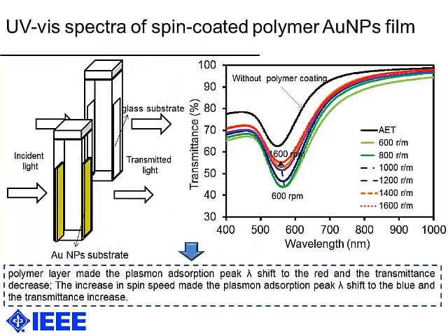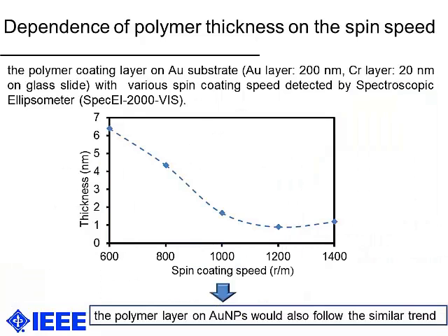And then we detected the spectrum of spin coating the polymer on AuNPs films with different spin coating speeds, shown like this one. The polymer layer made the plasmon absorption peak lambda shift to the red and the transmittance decrease. The increase of spin coating speed made the plasmon absorption peak lambda shift to the blue and the transmittance increase. And we used an ellipsometer to verify the dependence of polymer thickness on the spin coating speed. Here, the Au substrate is shown like this. The Au layer is 200 nanometers, and then we dripped the same amount of polymer liquid with different spin coating speeds. The thickness value is shown like this one. So the polymer layer on Au nanoparticles should also follow the same trend.